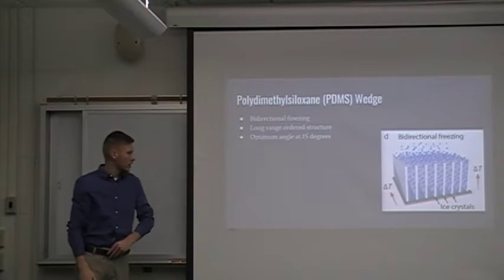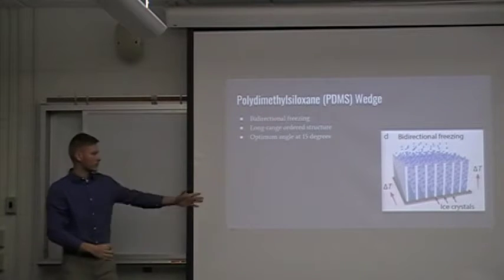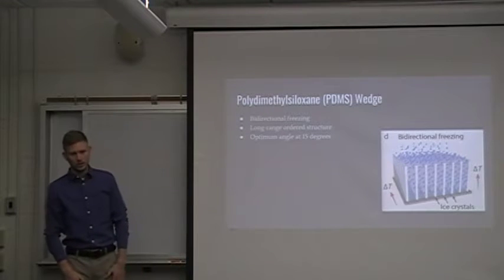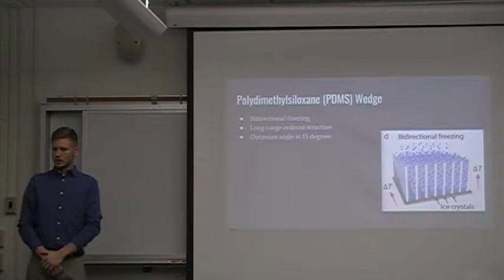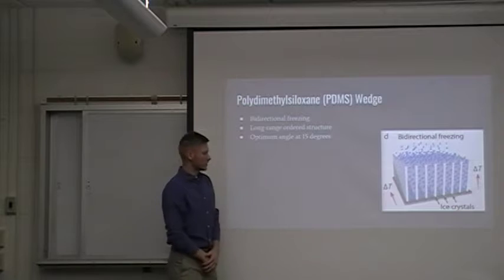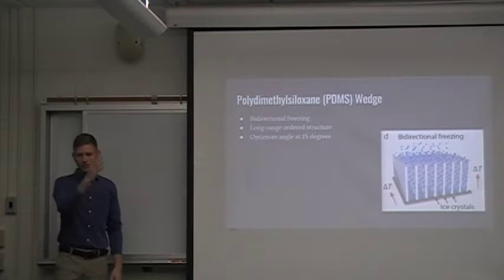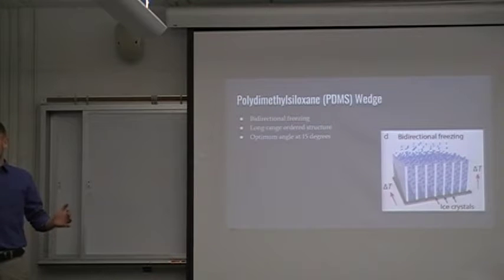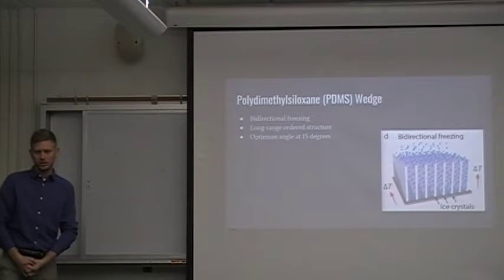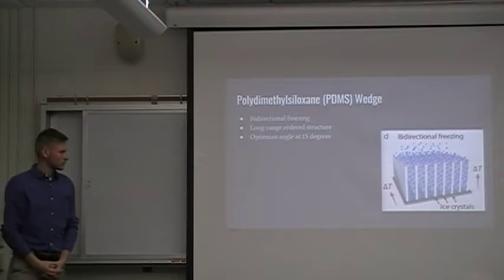They said it was cooled with negative 60-degree cryogenic ethyl alcohol, and it freezes through the wedge. Like the wedge conducts the coolness from it. So is the wedge at different temperatures, or is the wedge all the same temperature? Well, I would believe it would be at different temperatures with the delta T, as it goes up the suspension, but naturally through the process, by the end it's all solid, it'll all be at the same temperature. Okay, so it's cooler at the front, as we're looking at that picture, and warmer at the back, if you want to call it that. Mhm. Because the wedge is actually like an insulator, I think.